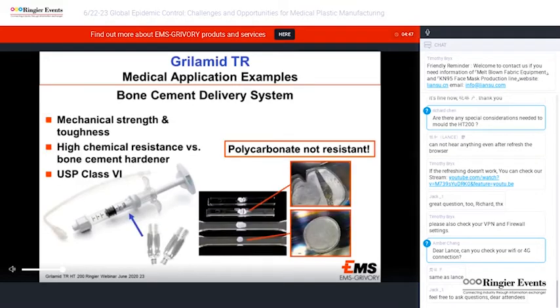Here we have a bone cement delivery system. The reasons Grilamid TR was chosen are similar to the previous example in regards to mechanical strength and toughness and chemical resistance. In this case, we require a good resistance against the bone cement, which is quite aggressive. On the right-hand side, we can see how this bone cement attacks polycarbonate, making it unsuitable for this application. Another reason Grilamid TR was selected for this application is its medical approvals, in this case USP Class 6 approval.